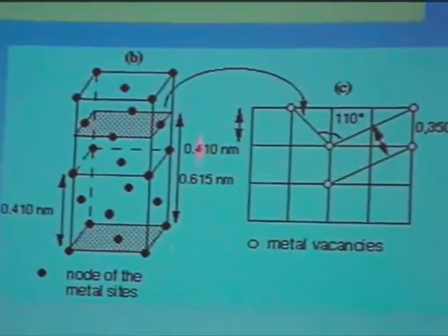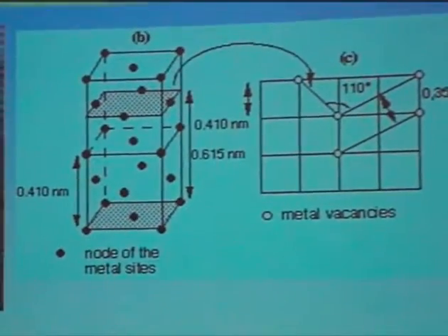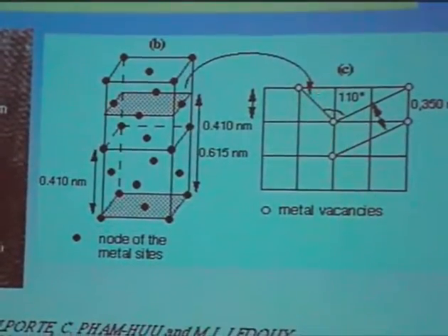But Teiichi came to our lab for a while. He was an invited professor with us, and he started to look at his crystallographic results, and he's a very good crystallographer, and he found a very nice explanation for this band. If you look at the TEM pictures of this oxycarbide, you see this chevron-like structure, and that is the crystalline structure that I have just described before. And if you make inside this crystalline structure these vacancies of molybdenum, which are these, if you look at the plane in this direction, you get this sort of configuration, which first